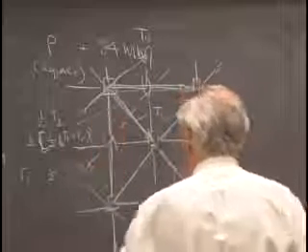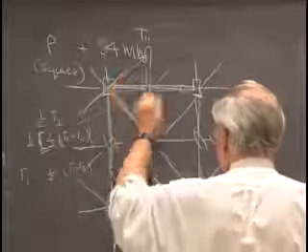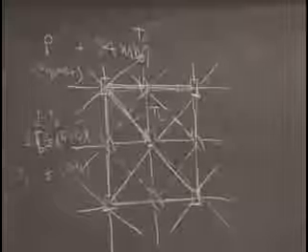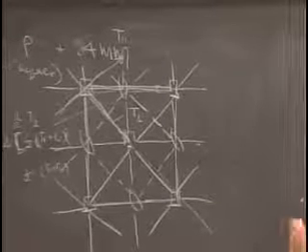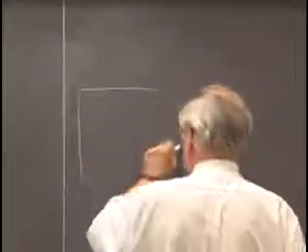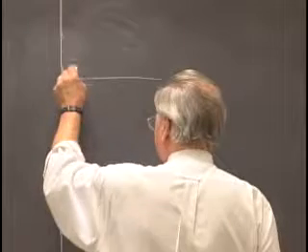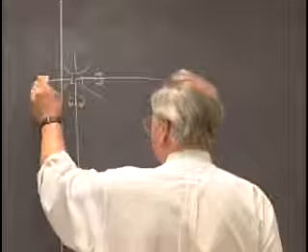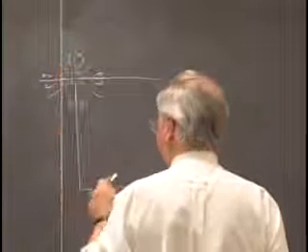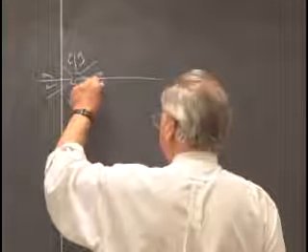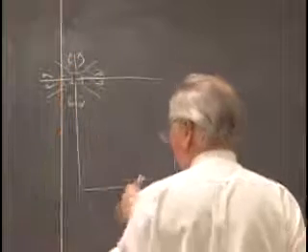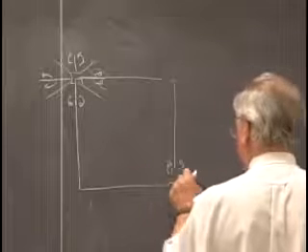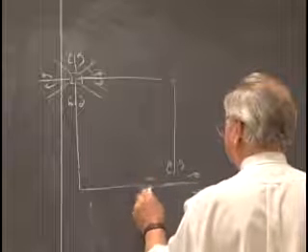So we get a new glide plane in here, and that will require glide planes through similar arguments that go down the diagonals of the cell like this. And let me convince you that that, in fact, is an operation that must arise if I place at the origin of the cell a set of objects that have 4mm symmetry. Okay, we'd have one like this, one like this, one like this, another pair hanging here, another pair hanging here. And if we do a reflection operation, let's say this pair up to this pair, and then slide it down by the diagonal translation, we have the same set again hanging down here at the diagonally opposed lattice point.